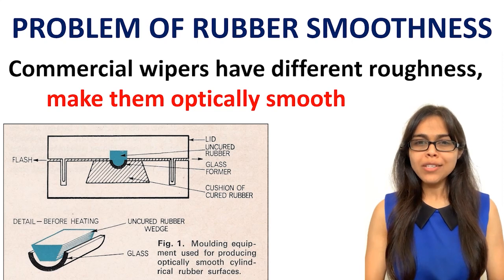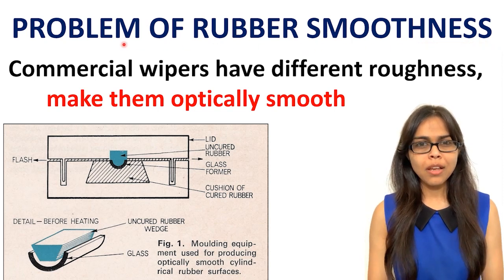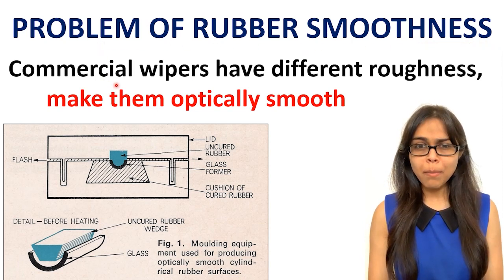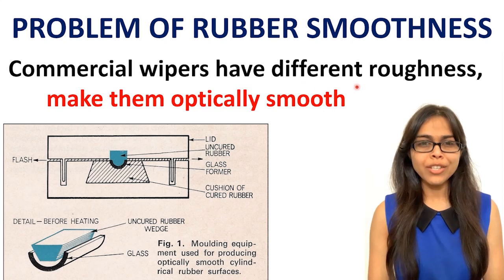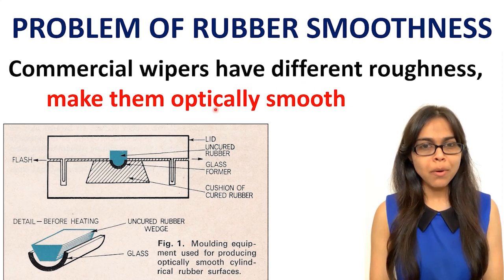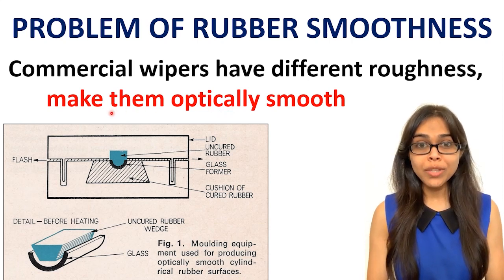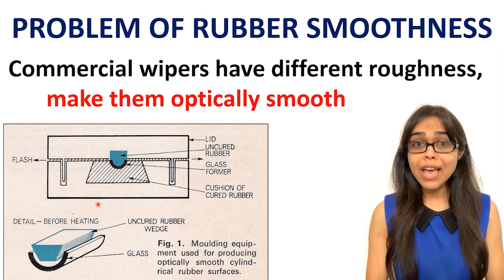One of the first problems Alan addressed was the variable roughness of commercial windscreen wipers. This made the contact between rubber and glass quite changeable. Therefore, Alan invented a way to mold the hot rubber in a glass concave lens to get an optically smooth and reproducible surface every time.